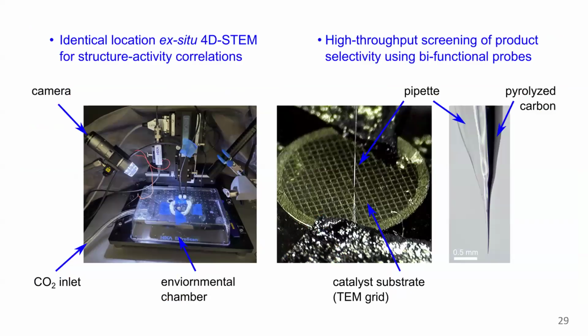So anyway, this is our instrument that we set up in December, so fairly recently. This is the SECCM platform, where we have our environmental chamber flowing CO2. Our preliminary experiments are on copper TEM grids, where we have a homogeneous catalyst. It's not a catalyst array, it's just a single material. We'll move on to arrays in the future, but as a proof of concept, doing this on a TEM grid also allows us to do a one-to-one correlation between the electrochemical activity and the catalyst structure, because we can do our SECCM experimentation, take the grid to the TEM, and then get catalyst structure.